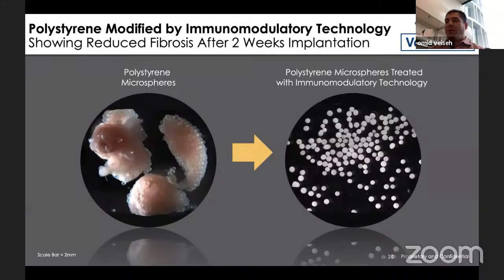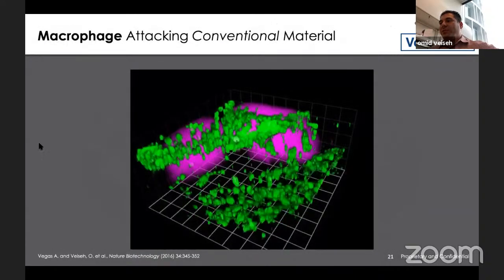We could take those same small molecules and actually apply them to a number of different types of surfaces. For example, here's a study we did with polystyrene microspheres. If you're familiar, polystyrene is the material that we use for tissue culture. It's a highly inflammatory material. It's a highly fibrotic material. When you implant it without any modifications, within 2 weeks, the mouse's immune system orchestrates a robust immune response, and all of the beads get engulfed in this scar tissue. When we take that small molecule and apply it to the surface of these polystyrene beads and implant them, the material looks like it did before it went in. So, a dramatic reduction in immune recognition and fibrosis, and we can apply this to a number of different substrates.